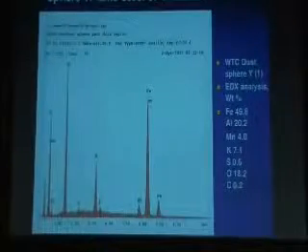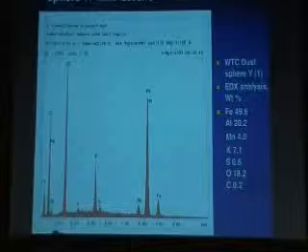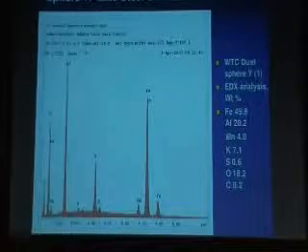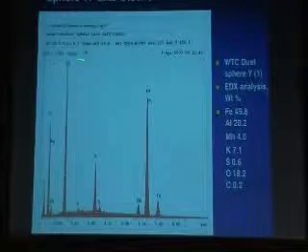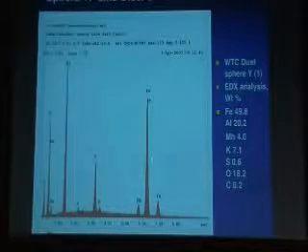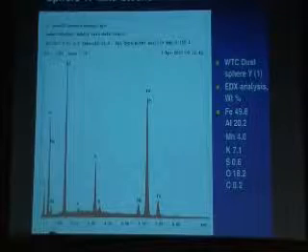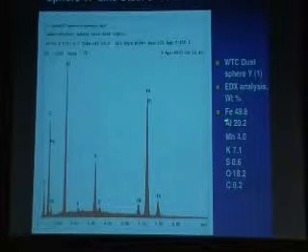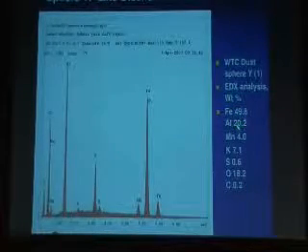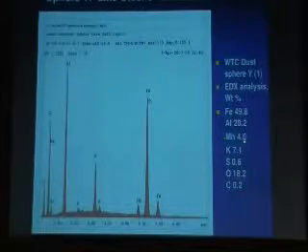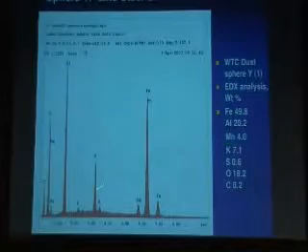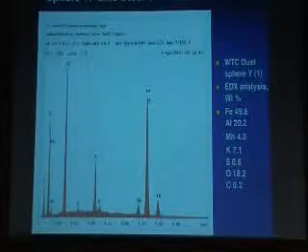Now, something new as we look at these tiny spheres. This is sphere Y. Does it look like thermite? Does it have the basic signature? The answer is yes. The aluminum peak there, and iron, and sulfur. Iron, about 50%, aluminum, about 20%. Very typical for thermites also. Now we have a lot of manganese and potassium. Look at that showing up.